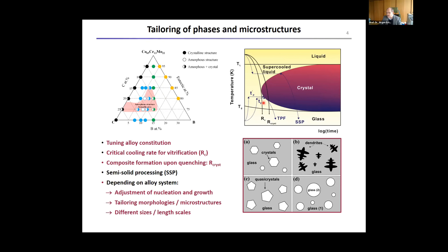On the right-hand side, this sketch gives you an idea about a CCT diagram. If you come from the melt and quench at different cooling rates, you may have the chance for a given composition to form a single-phase glass — if you quench fast enough to bypass the nose — or if you quench slower, you may hit the nose and have a combination of an amorphous matrix plus whatever crystalline phases, typically metastable phases expected from the phase diagram at high temperature, or you could have it fully crystalline.